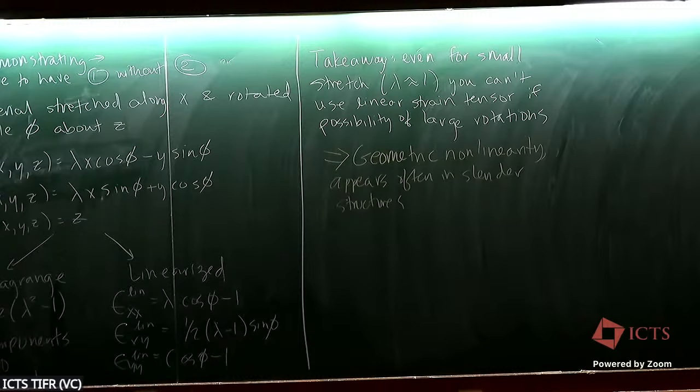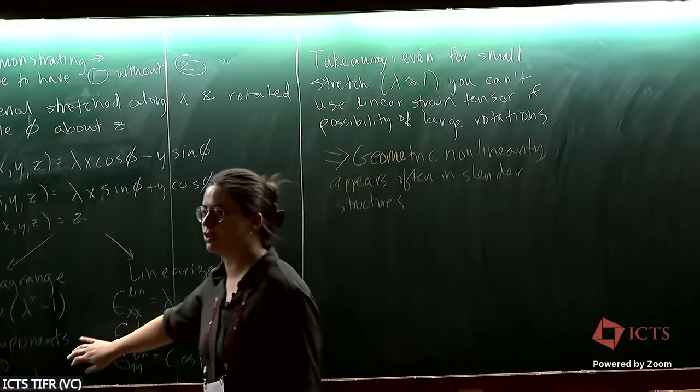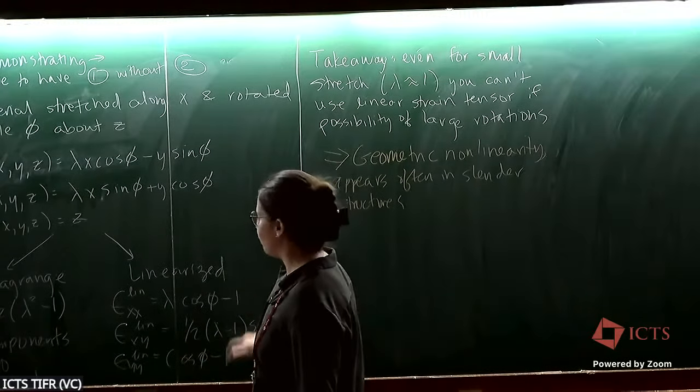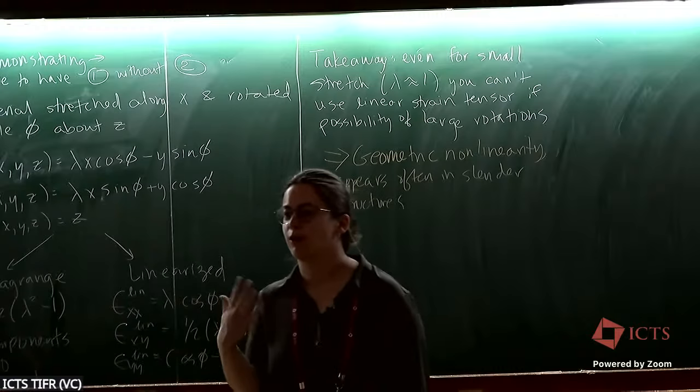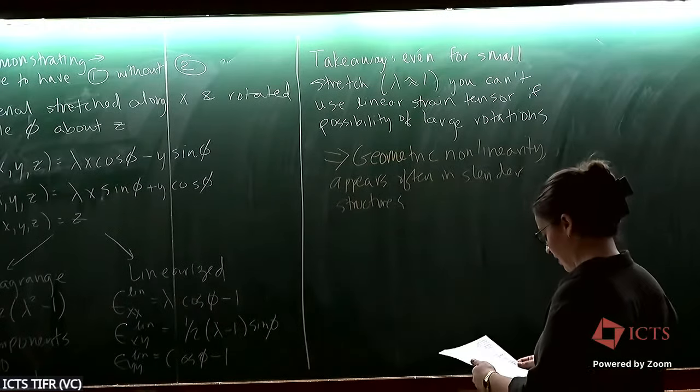We can assume that there's very little stretching. And so this is an example where you can think about this material rotating. You're getting these large slopes, and you need to include a geometric nonlinearity, or else, and this is something that really shows up quite a lot in computation as well, you can get results that look real, but you're using a completely wrong strain tensor, so they're picking up stresses that don't exist when you have these large deformations.